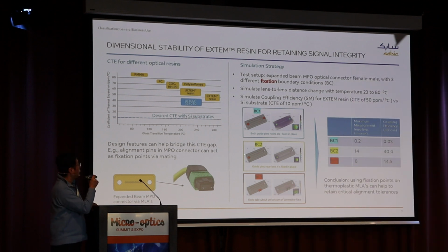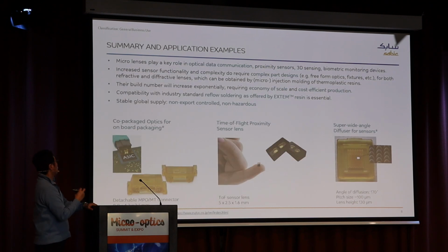In these 2 cases, we only restricted the expansion on one side, then they can freely expand and shrink. Then you can see a lot higher lateral misalignment and signal loss. But by constraining the expansion, it will bulge in a 3-dimensional direction. But laterally, these lenses are still aligned to either the fiber side or the PIC side, and you can still see very minimal signal loss. So in this talk, we mainly talked about this thermoplastic resin solution, which is reflow compatible, for